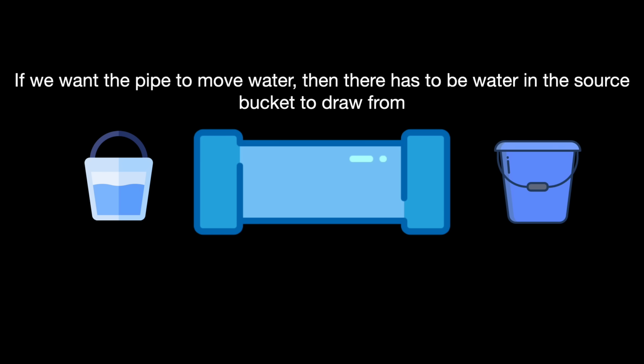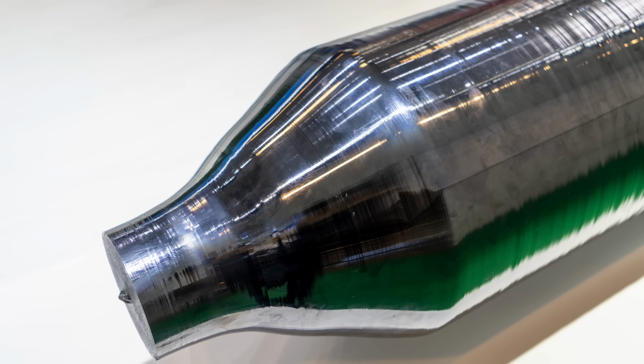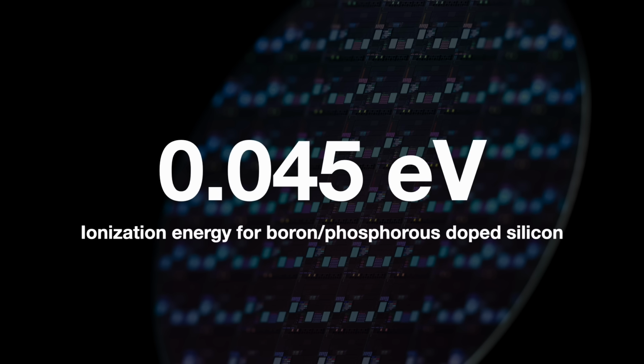but it does not. If we want to imagine the transistor as transporting water from the source to the drain through the channel, we need to make sure that there is water in that source. With silicon, there is plenty of water, meaning charge carriers, available. The boron and phosphorus atoms inside the silicon are willing to give up their charge carriers when given just a small amount of thermal energy. At about 0.045 electron volts for both boron and phosphorus, silicon's ionization energy threshold is low enough, or shallow enough if we're to use industry lingo, that room temperature works.